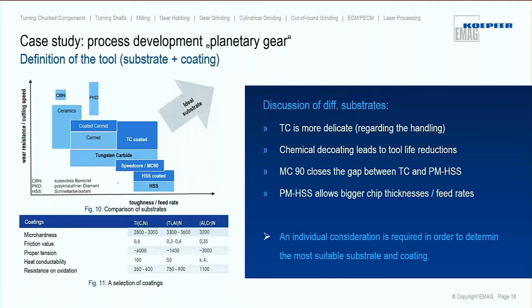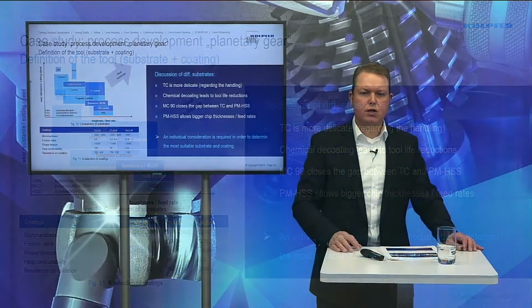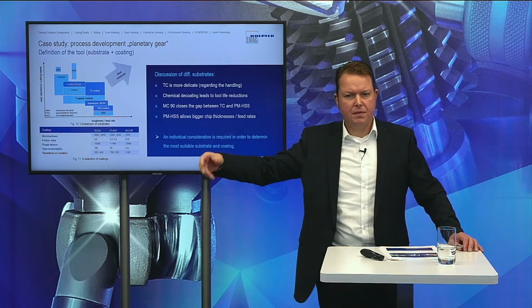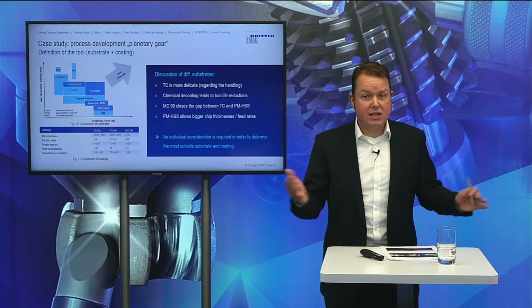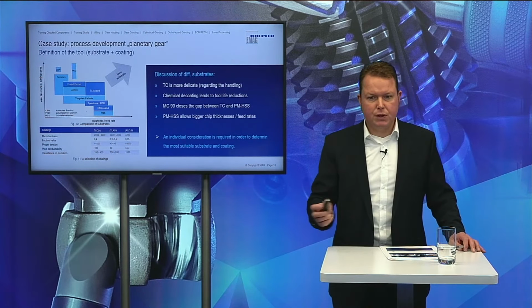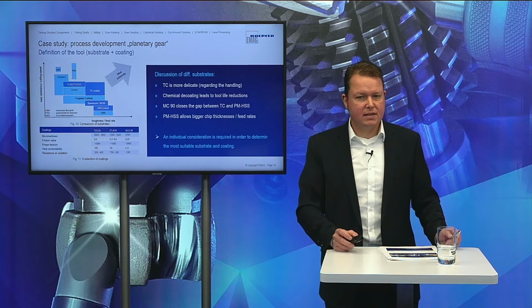When we discuss the different substrates, we should also think about how to do the manufacturing of the tools, and we have to consider that with tungsten carbide, chemical decoating may lead to a tool life reduction if it is not made properly. How do we do the decoating of a hob? Usually the hob is used, it is worn, we have to decoat it, and so we put it into an acid bath, and it stays there for many hours until the hard coating dissolves and goes away. And this chemical bath may attack the cobalt basis of the material, and this may lead to a reduction in tool life. So over the life of a tungsten carbide hob, this effect may lead to a reduction of tool life. This is something that we have to be aware of and that we have to consider. But for the choice, an individual calculation and consideration is necessary, and we are going to do this afterwards.